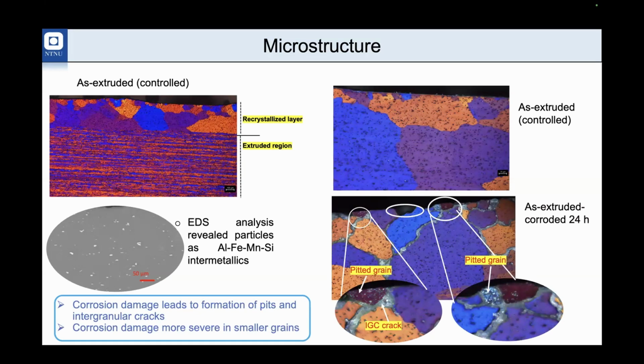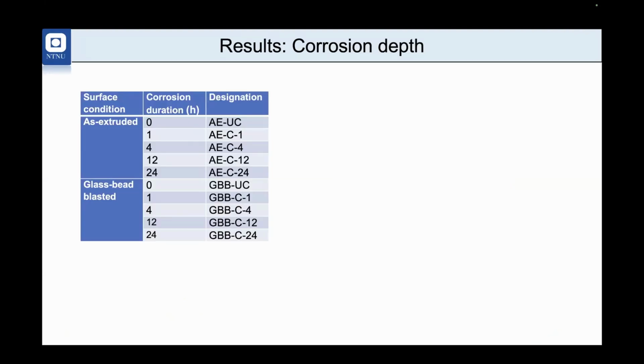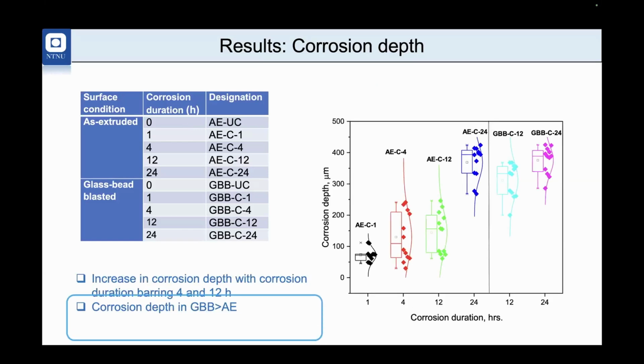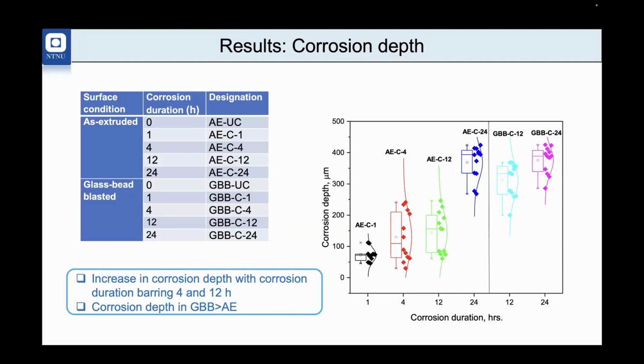In contrast, if you see the microstructure of the corroded materials, it is different. You can see there is significant intergranular corrosion, with pits appearing especially in the surface region in the smaller grains, and intergranular cracks appearing from there and moving towards the interior. We have used this designation so that we can characterize the conditions better for different corrosion durations. In this slide, I just want to show some of the corrosion characterization in terms of maximum corrosion depth. If you look at the graph on the right-hand side, we have done quite a detailed statistical analysis. We have taken the corrosion measurements on the front and the back side. This is the box plot, which shows that with an increase in corrosion duration, the corrosion depth increases.